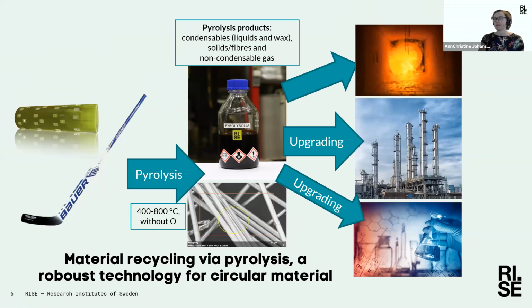We have used pyrolysis, which is a thermochemical process where we heat the material somewhere between 400 to 800 degrees C without adding oxygen. And then we more or less separate the incoming product. We receive the fibers and we also receive pyrolysis vapors. The pyrolysis vapors are then condensed to a liquid, but it could also be a wax for some kinds of materials, and the non-condensable gas.